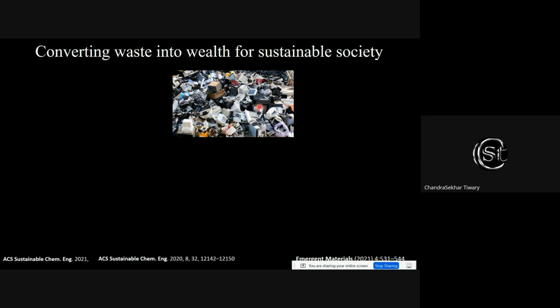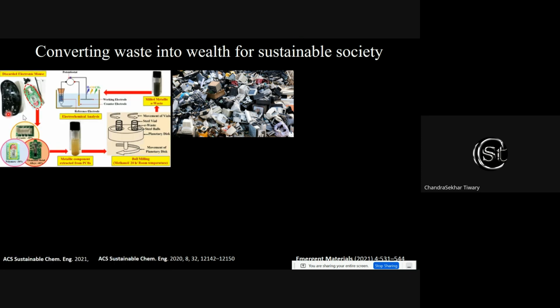I started working on electronic waste in 2015, where we showed for the first time that you can take this electronic waste and take out the most complicated component, which is the PCB. Now, the PCB is interesting because it has all different kinds of material. For example, it has metal, ceramic, and polymer. Separating them individually is difficult. So most electronic waste recyclers take out the gold and silver and dump the rest. We take this whole electronic waste, crush it in our ball mill, and make it into a powder form.